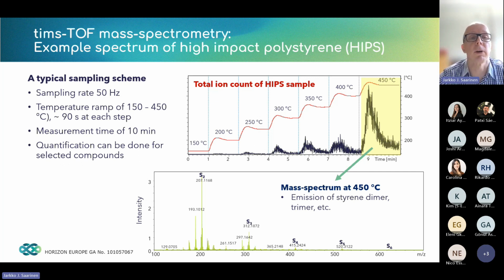In the case of high impact polystyrene, what we typically see is the emission of the styrene dimers here at 207, then the trimer at 312, and then multiple compounds of the styrene units. Also, what is important is that typically mass spectrometric tools are considered to be only qualitative in nature, but we can also do quantification of compounds, at least on the semi-quantitative stage. This is something that we have also been developing within the Primus project.